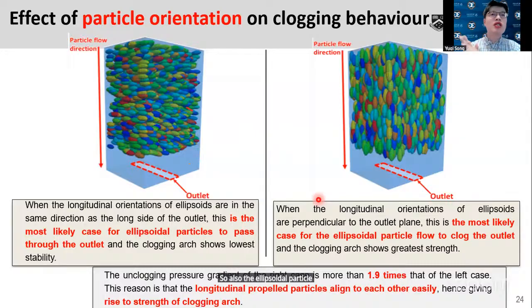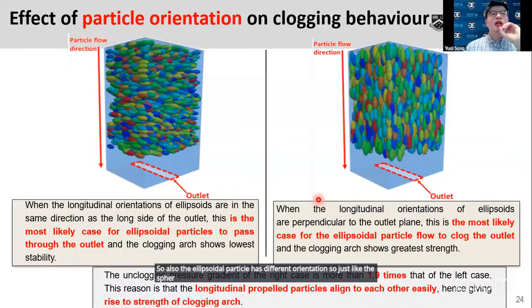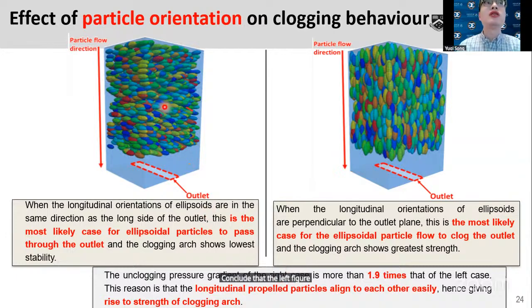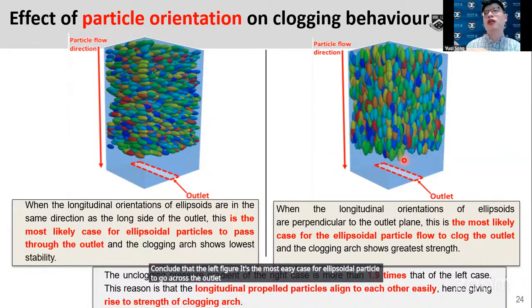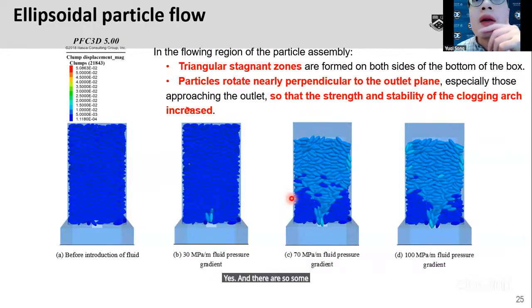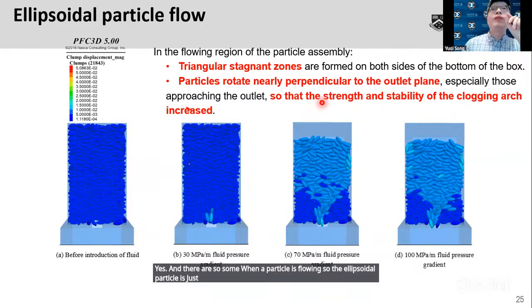Also, the ellipsoidal particle has different orientations, just like the spherical particle. When we change the orientation of the ellipsoidal particle, in the left case the particle is aligned in this direction, and the right case is in the direction perpendicular to the outlet plane. We can conclude that the left figure is the easiest case for the ellipsoidal particle to go across the outlet, but the right figure is the most difficult case, and the difference is 1.9 times in clogging arch strength. When a particle is flowing, the ellipsoidal particle turns to its flowing direction. That is one phenomenon.